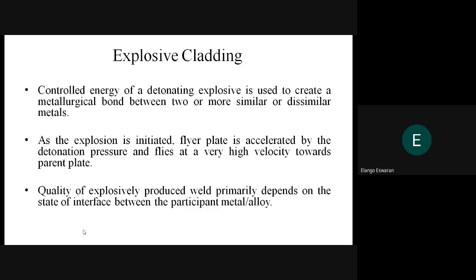Explosive cladding, a solid-state autogenous metal joining technique, employs an explosive force to craft an electron-sharing metallurgical bond between dissimilar metals. Controlled energy of a detonating explosive is used to create a metallurgical bond between two or more similar or dissimilar metals. As the explosion is initiated, the flyer plate is accelerated by the detonation pressure and flies at a very high velocity towards the parent plate. Quality of explosively produced weld primarily depends on the state of the interface between the participant metals and alloys.